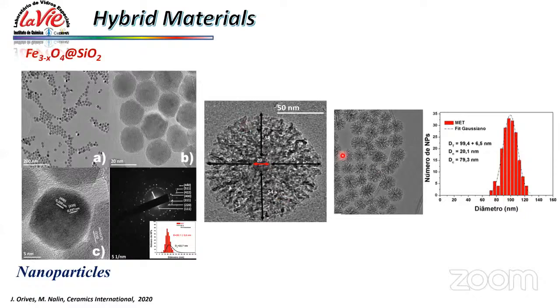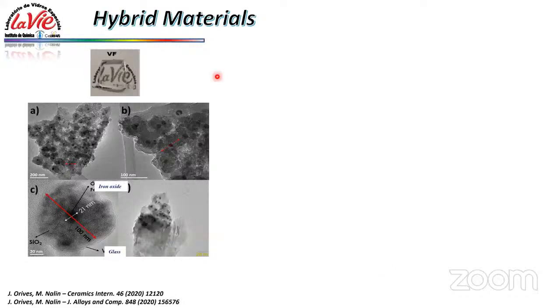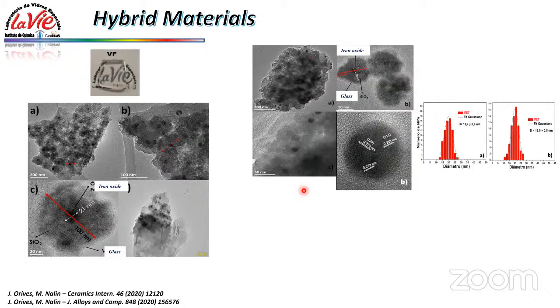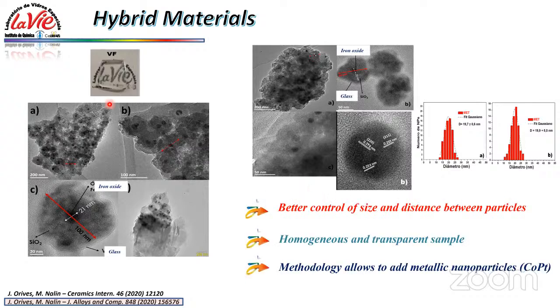These nanoparticles were monodispersed, and then when you disperse them into the glass, we did the same procedure as I showed you before. So we got some samples like this with the nanoparticles inside the glass, and the shell was still here. We could identify that some silica dissolved into the matrix, but it was not so bad because in fact it stabilized the phosphate glass. So we could find the nanoparticles inside the glass. With this kind of approach, we could have a better control of size and distance between the particles.